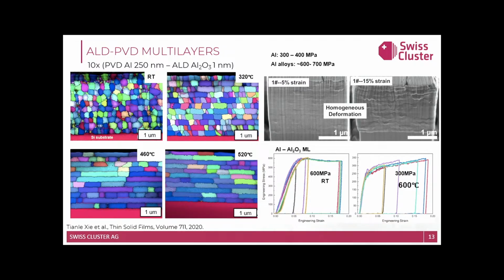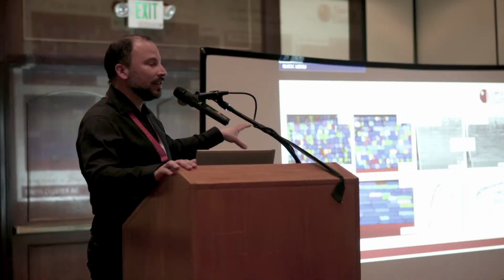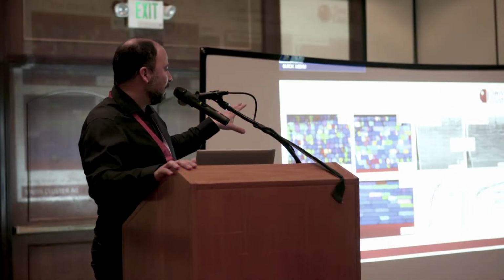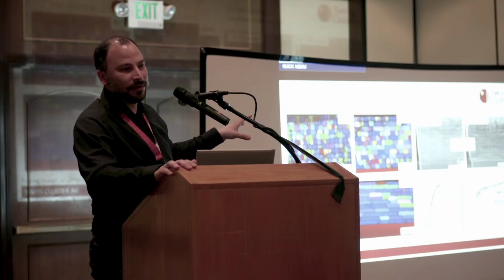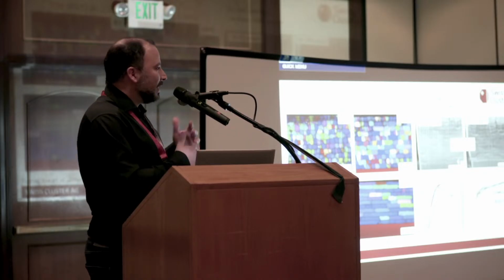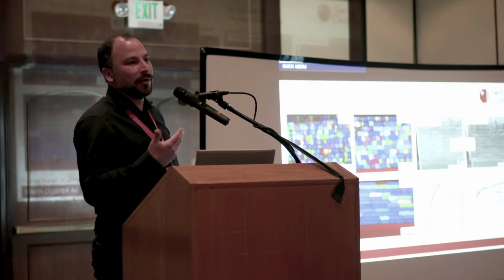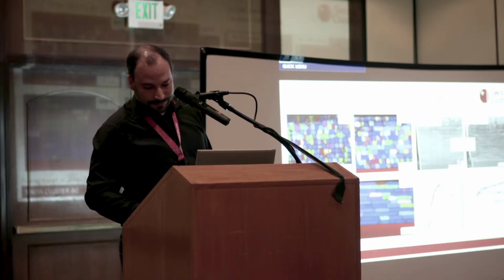Is it better? So the ALD layer also minimizes the grain growth in the lateral direction, right? And because we can retain this microstructure at these high temperatures, we can have 50% of the mechanical performance of the original coating, right? So this type of strategy can improve the operating temperature of existing coatings.